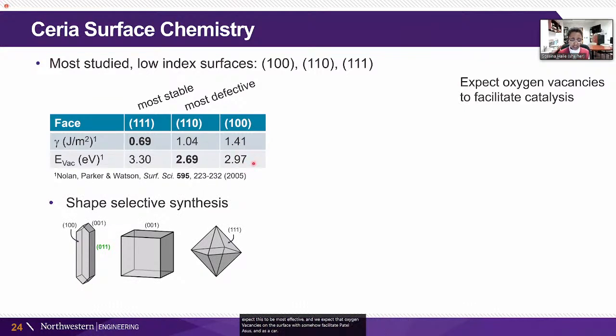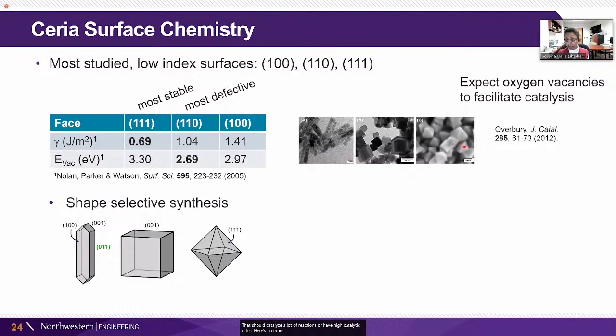And as a consequence of that expectation, there is a lot of interest in doing what's called shape selective synthesis of ceria to be able to create, in particular, this kind of structure, which has a lot of the 110 or 011 phase that should catalyze a lot of reactions or have high catalytic rates. Here's an example from Overbury's lab from several years ago, where you have a lot of 011 termination, a lot of 001 termination, and then a lot of 111 termination.